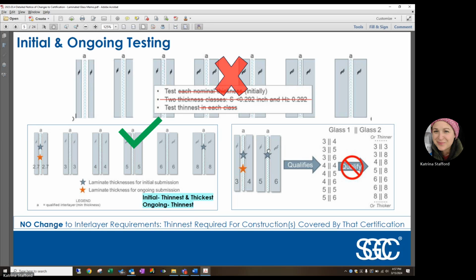Another way of displaying this here to the right is showing that a 3 and a 4 mil were tested for the thinnest configuration, and a 5 and a 6 mil for the thickest configuration using the same interlayer thickness. Displays to the right what thicknesses you're qualified to make, along with what thicknesses you are not qualified to make. So a 3 and a 3 would not be allowed because you did not test the 3 on the outboard light for your thinnest configuration. It also shows you that if you try to surpass a 5 or a 6 for your thickest configuration, that's not allowed either. You can't use, say, a 6 and a 6 because you did not test with a 6 and a 6. You only tested with a 5 and a 6.